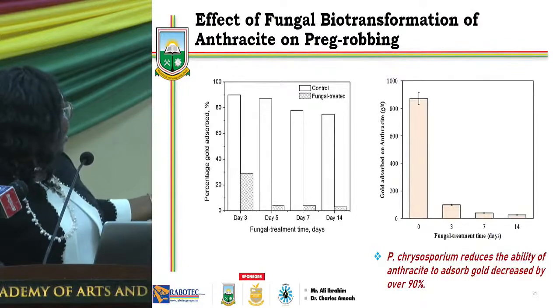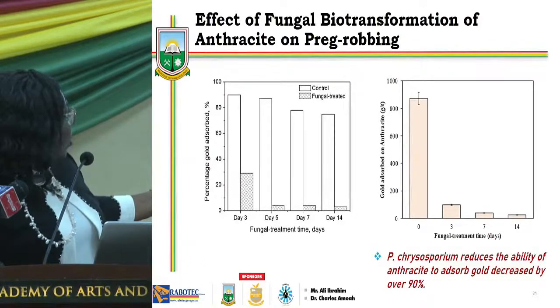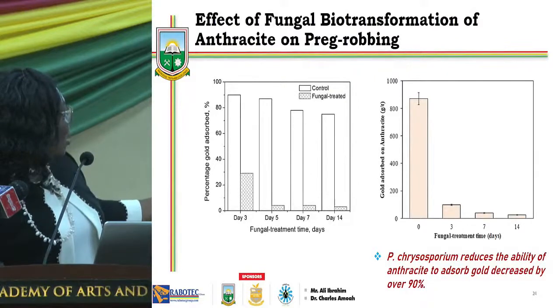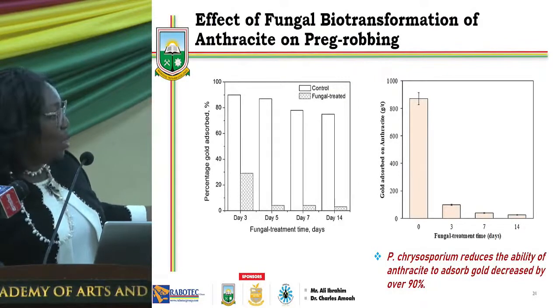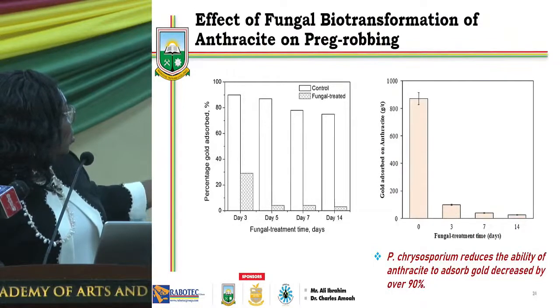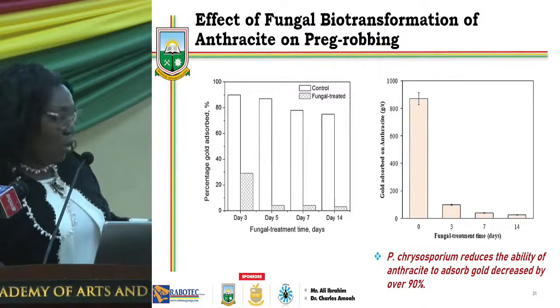Then the second diagram is also showing gold absorbed on anthracite in gram per ton. And we are looking at the number of days used in treating the carbon. So we see that the as received absorbed as much, and as a result of the treatment, gold absorption on carbon reduced.